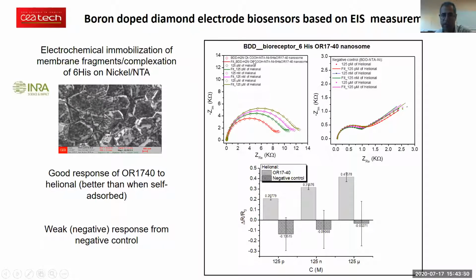So as we expose this sensor to different concentrations of Helional, we have some change in the conformation of the protein that will affect the transfer resistance of our electrode. And you can see that if the concentration increases, we have an increase in the transfer resistance of our electrode. So we do have a sensing signal. And you can see that we can get down to the picomolar range. So we are extremely sensitive to our ligands here.